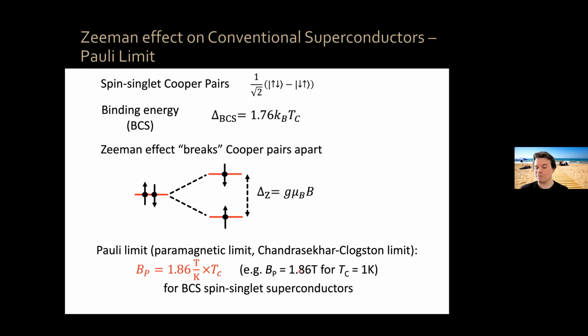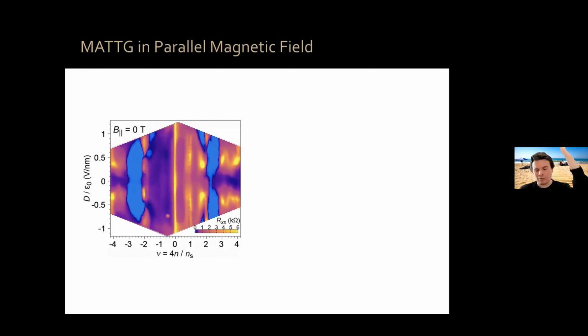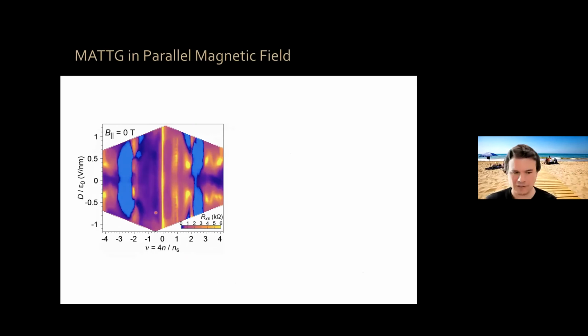So let me show you what happens in trilayer graphene. We warm up our sample, we rotate it, and we cool it down in a system where we can apply an in-plane magnetic field. These are the data at 0 parallel magnetic field, very similar to before. I think you recognize it from earlier. Now, here at optimal doping and optimal electric field, our critical temperature was about 2.7 Kelvin in this cool down. That means that the Pauli limit should be about 5 Tesla. By 5 Tesla, superconductivity will be completely gone, okay?